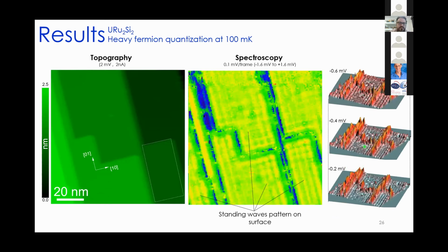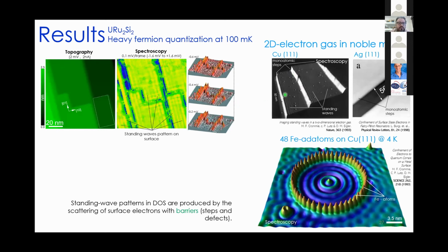Let me put this in this form here. We plot just some of the energies as a function of the bias voltage, and you can see here just the kind of ripples of the waves on the different terraces that we get here. And to explain this, let me remind that the pattern that we observe here is so similar to patterns that have been observed in noble metals like copper and silver. And maybe the most popular standing wave pattern observed using an STM is this one, the quantum corral that was made by iron atoms on a copper surface. We have the same, but we don't have circular quantum corrals, we have square quantum corrals. So these patterns in the density of the states are produced by the scattering of surface electrons with barriers like steps in our case or defects like this one.